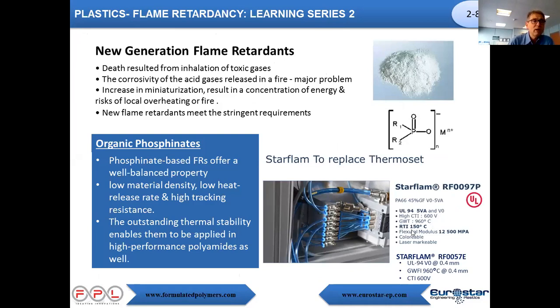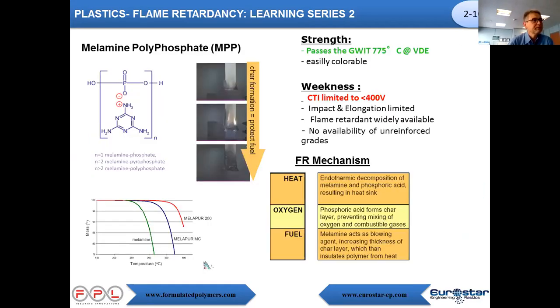And from this, we have a real nice range at Formpoly and Eurostar of material, which are UL listed in 6.6 with glass fiber from 20 to 45%. And it's really the more, let's say, up-to-date formulation for us. Melamine phosphate, I will go very fast because this one is a kind of derivative of the previous one. It's just pure melamine polyphosphate, and the single interest of it is that it passes the GWIT for people who are working for appliances, what we call white goods.